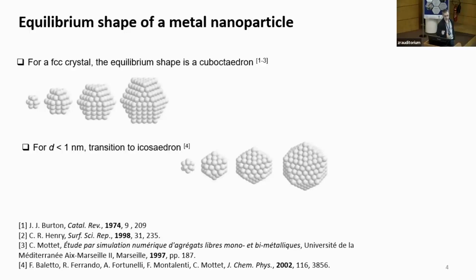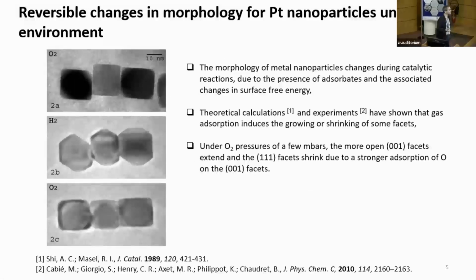But this is true for 0 K, and this is true for vacuum conditions. And these are conditions which are very far from what we are doing in gas phase catalysis or in electrocatalysis. Let me show you, for example, what happens when you change the environment, and these are the associated changes in morphology. So cubic platinum nanoparticles turn more rounded under hydrogen, and these changes are reversible, and this is basically the same particle under oxygen again. So some facets are just shrinking, some others are just expanding, right? And so thermodynamics cannot give you any insight into this.